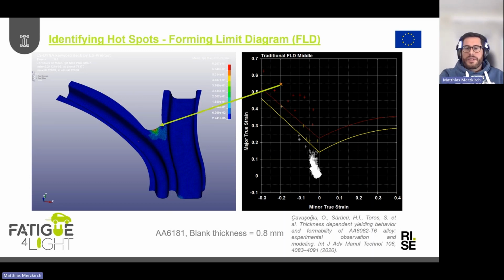If we have a closer look into this forming limit diagram in order to understand the actual forming behavior, we don't have to go actually in different areas because we have a more or less concentration in this area here. Well, and if we compare that to uniaxial testing, of course, that cannot cover everything, but at least we can play a little bit. What should we do in order to avoid this cracking? Although here we actually see it was already reduced compared to the video shown. So how can we change that?